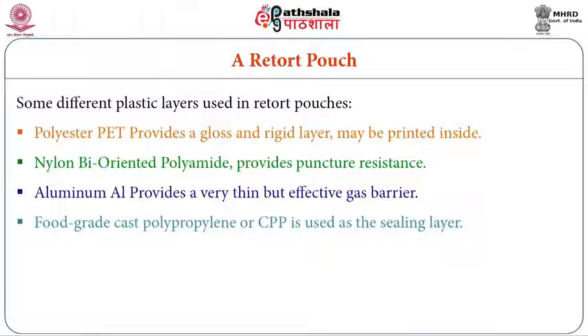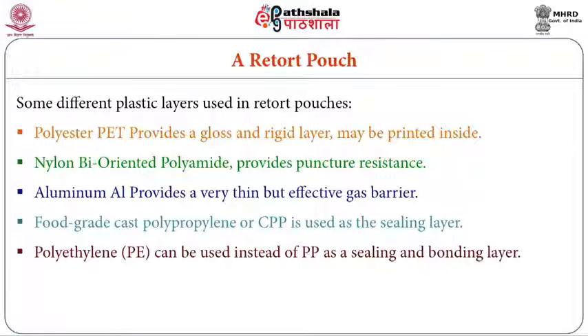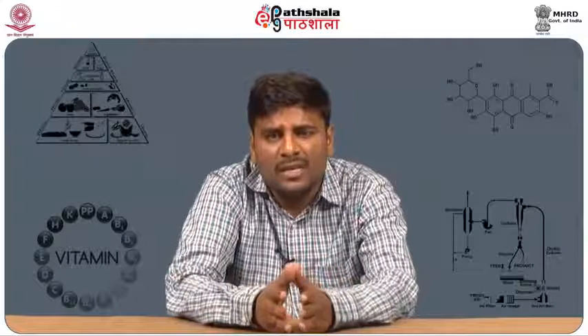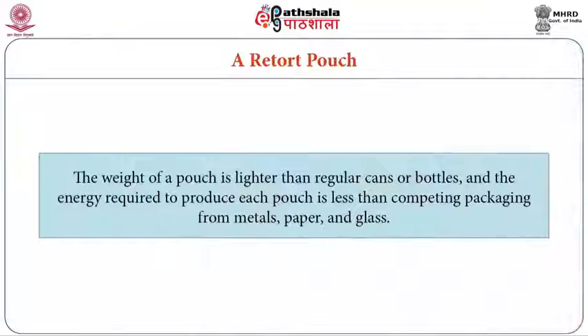Next, food grade cast polypropylene or CPP is the important layer. It is the sealing layer we use, and polyethylene can be used instead of polypropylene as a sealing and bonding layer. These are the layers we co-extrude together, and after co-extrusion we call it a laminate. In that laminate we fill the food items. The weight of this pouch is lighter than regular canning bottles, glass bottles or any other plastic bottles, which brings convenience to the customer.